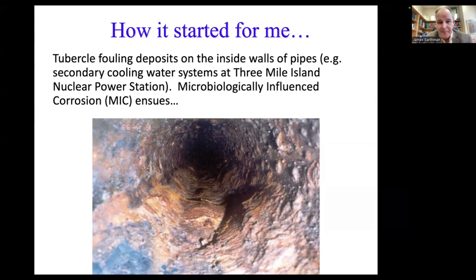And these tubercles can form on the pipes in that secondary system. And once they form, they are very tenacious. This is actually after they tried to remove the tubercles during a routine shutdown of the plant. They took spheres with sandpaper on them. They flushed them through the system to knock the tubercles off. But that, as you can see, it didn't really do much in terms of removing them.